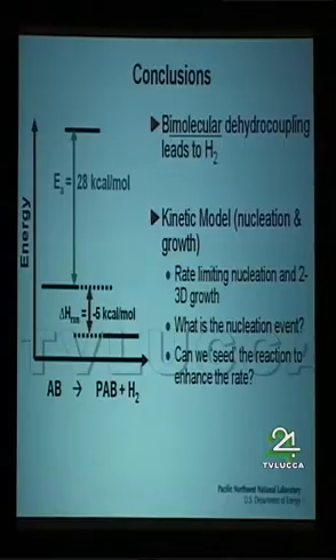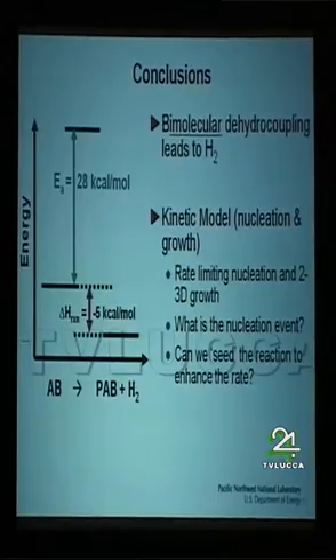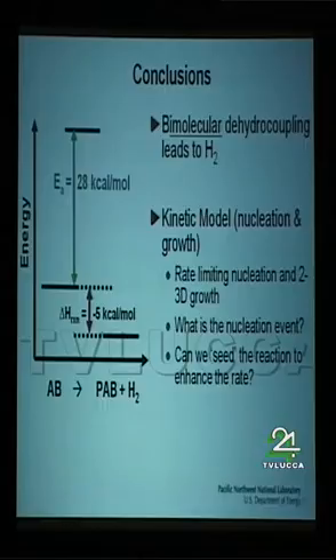And so that's going to make it a lot harder to just pressurize to put the hydrogen back on. But with some of the work we've done with the scaffold material that we've published, and it was on the poster, the enthalpy actually changed to almost thermal neutral. And so we're pretty excited to demonstrate for the first time that you could just pressurize this and see hydrogen go back on. We have a Sieverts apparatus coming from Carl next month, and we want to do the measurement at high enough pressure so we can demonstrate this reversibility. It'll give us some more information about the enthalpy.